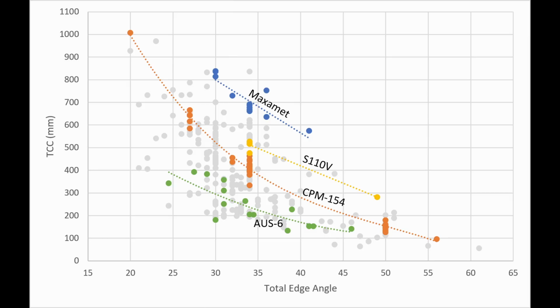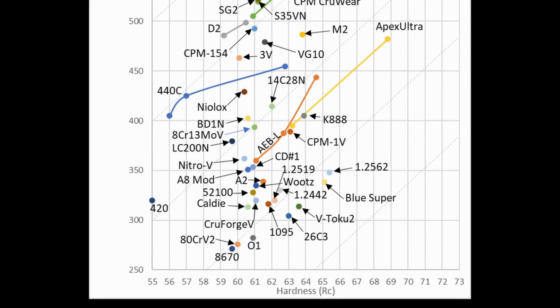Custom knives are often given thinner edges than factory-made knives. In general, when someone measures superior edge retention performance in a custom knife, it is because of better edge geometry, rather than any kind of super unmatchable heat treatment that you can't get in the factory knives. When a custom heat treatment does perform better with identical edge geometry and steel, it can usually be attributed to higher hardness. In my own Catra experiments, the effect of hardness is greater than other changes to the heat treatment that I have tested. So this is unlike toughness measurements where I have found significant differences when I've changed heat treatment variables. With edge retention, it seems to be more about hardness and the steel choice.